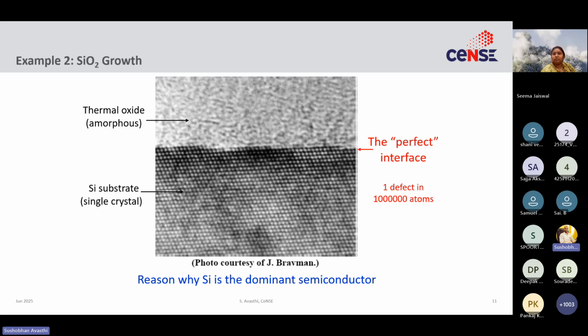The first semiconductor was actually germanium. If you go back and look at history, the first transistor was demonstrated on germanium. Germanium arguably has slightly better electronic properties. What germanium, however, doesn't have is as good a quality insulator as silicon dioxide is to silicon. The silicon dioxide interface for all practical purposes is defect free.